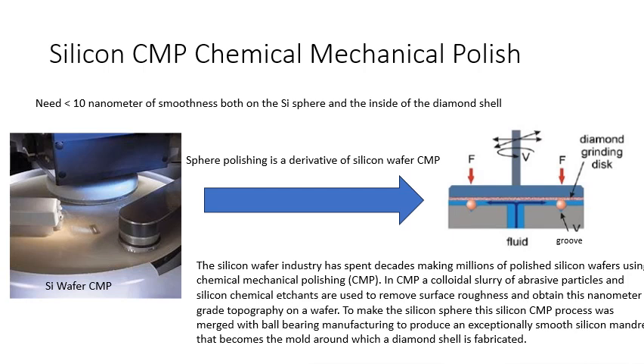Now this kind of tooling has been modified to polish these silicon spheres, and that's shown on the right. You've got this grinding disc on the top, which is the polishing pad. You've got some colloidal slurry materials with abrasive materials and chemicals that etch silicon. And then you've got a groove track where you put the silicon spheres, and you just polish away, almost like a rock polisher in a way of thinking.